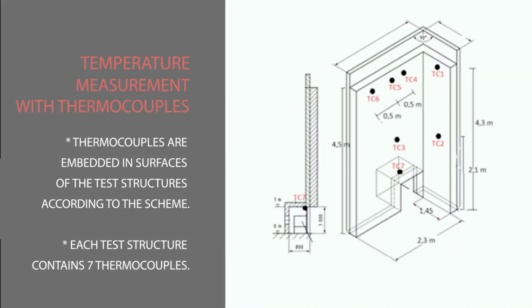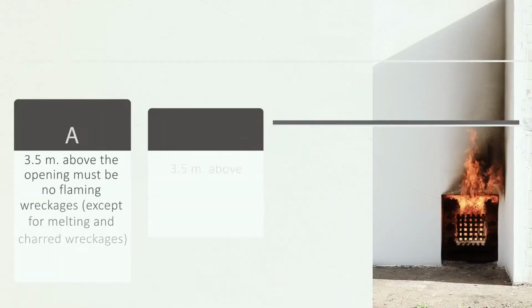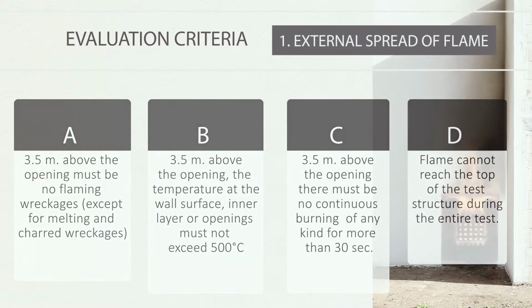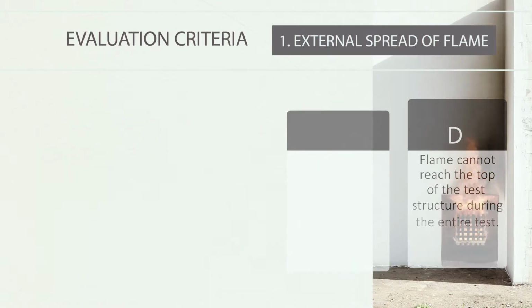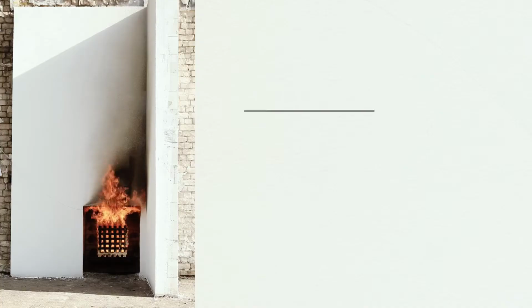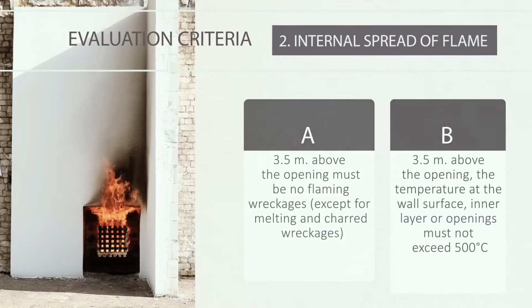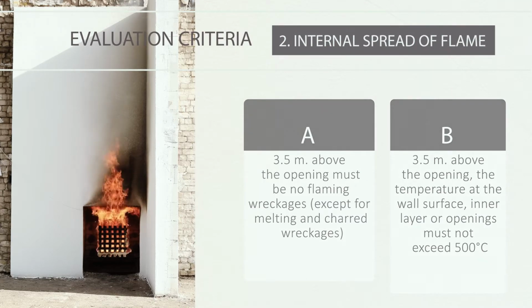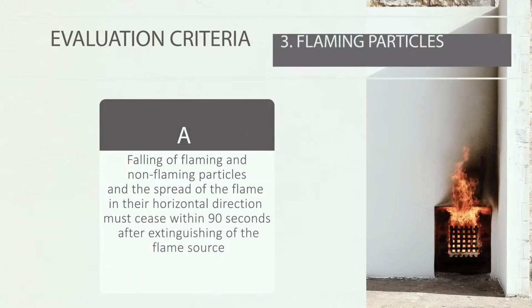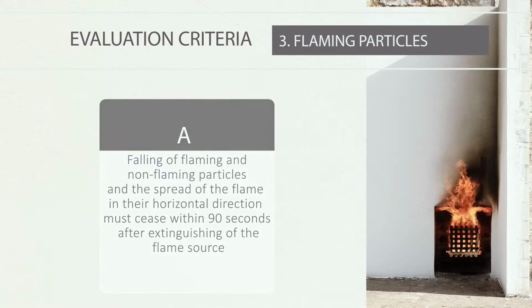Thermocouples are embedded in surfaces of the test structure. Assessing the external spread of flame: at 3.5 meters above the opening there must be no flaming wreckages, no temperature exceeding 500 degrees Celsius, and no continuous burning of any kind. Assessing the internal spread of flame: at 3.5 meters above the opening there must be no temperature exceeding 500 degrees Celsius. For the assessment of flaming particles, falling of flaming or not flaming particles must cease within 90 seconds after the flame source has been extinguished.